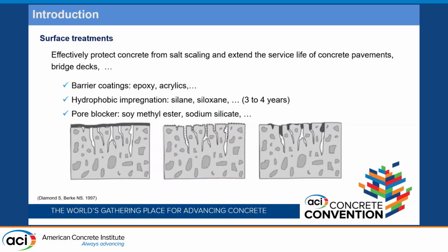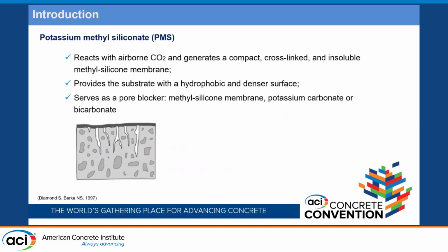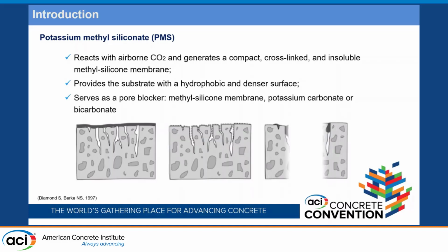So is there a surface treatment that can achieve all those functions together? The answer is yes. It's known as potassium methyl siliconate, PMS sealer. This kind of sealer will react with carbon dioxide and generate a very compact and hydrophobic film on the surface. It will also generate some hydration product like potassium carbonate and block the pores and the tunnels to achieve very good water resistance.